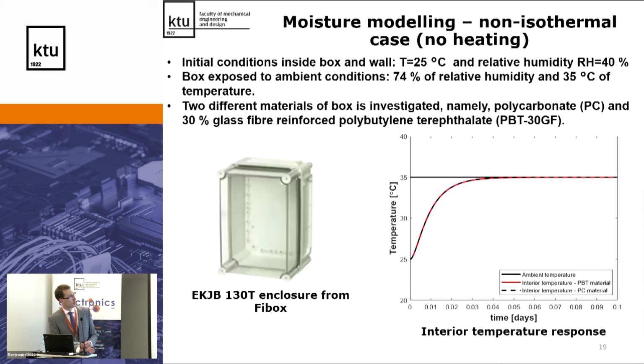Then I would like to show some moisture modeling on the non-isothermal case, where we have initial conditions of 25 degrees and initial relative humidity of 40%. Then the box was exposed to 74% and 35 Celsius. Here we take the same box, but we investigate two different materials, namely polycarbonate and 30% glass fiber reinforced polybutylene terephthalate, the abbreviation of which is PBT30 GF.